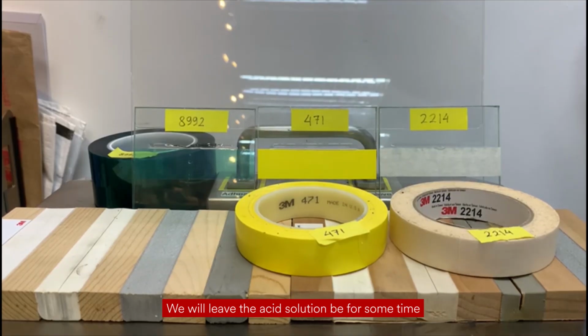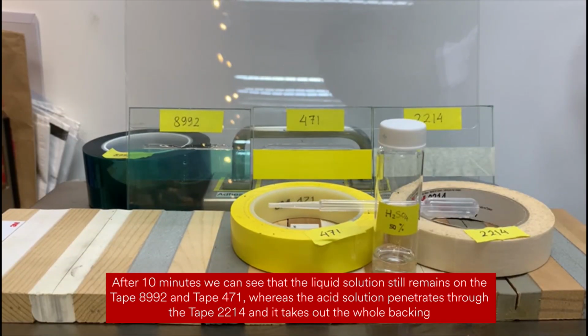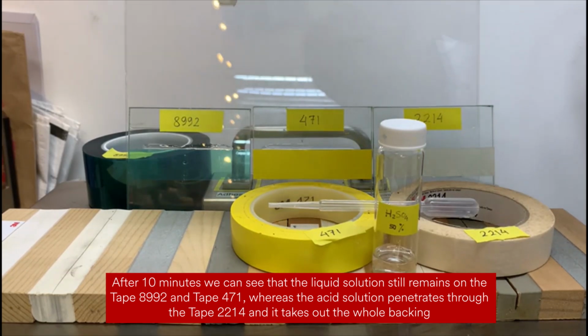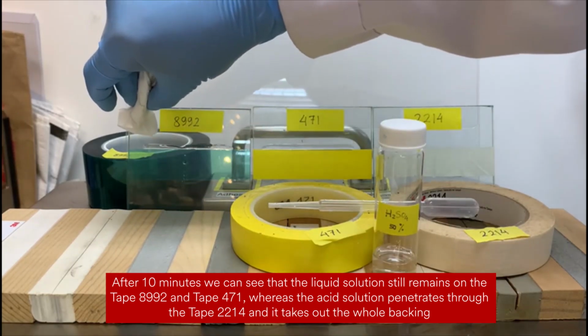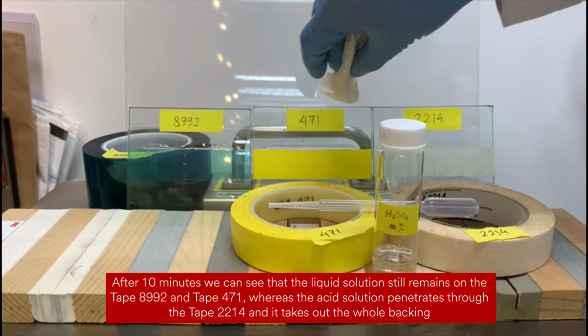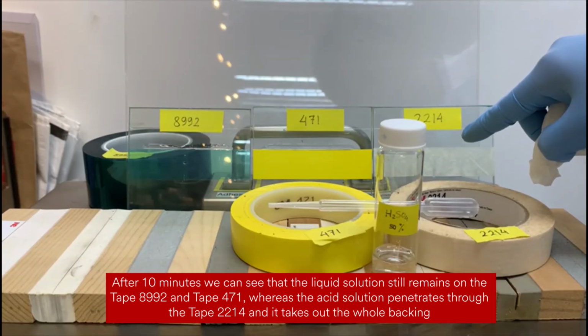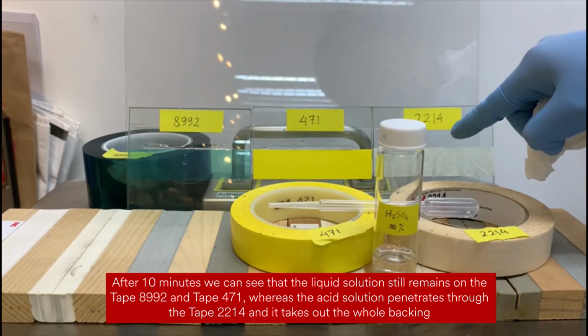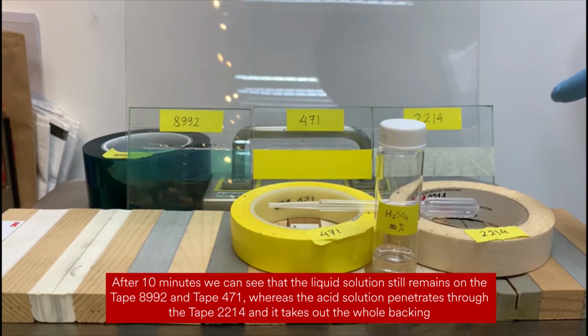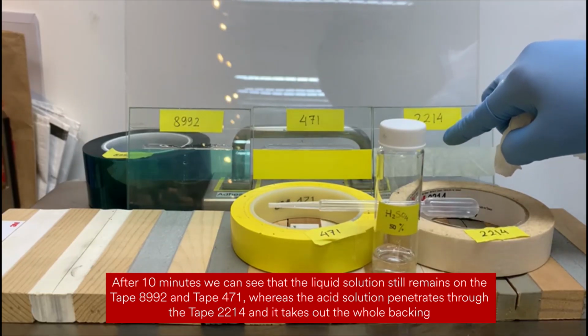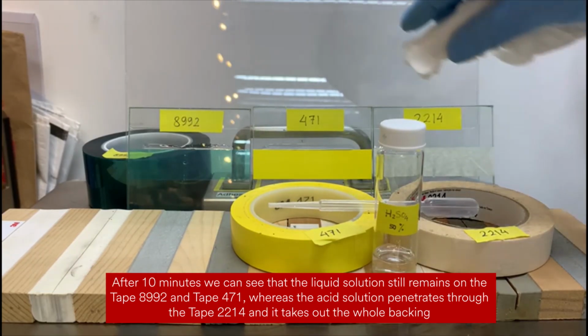So we will take some time to let the acid solution sit there. After 10 minutes, we can see that the liquid solution still remains on tape 8992 and 471, whereas the acid solution penetrated through tape 2214 and wet out the whole tape backing.